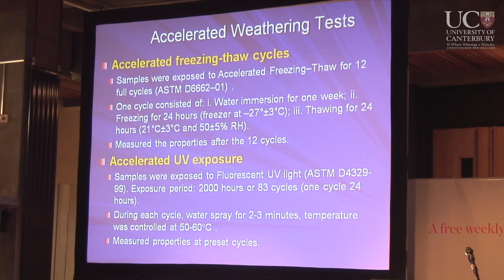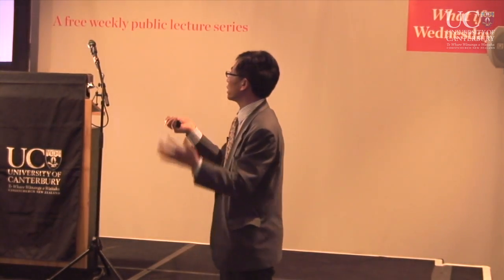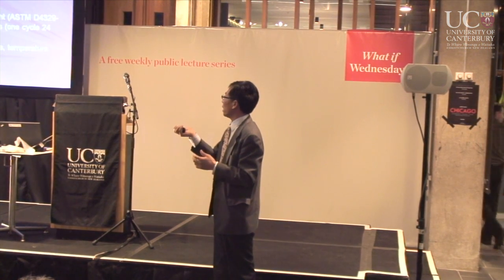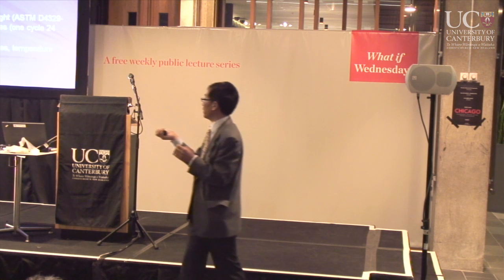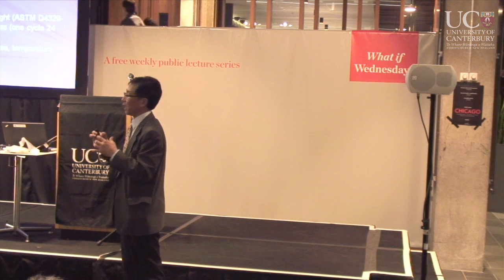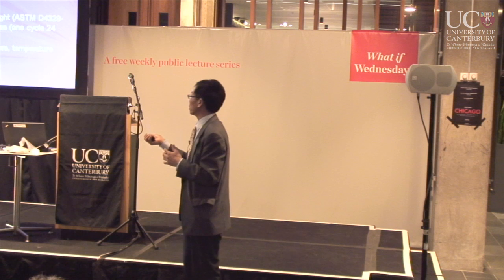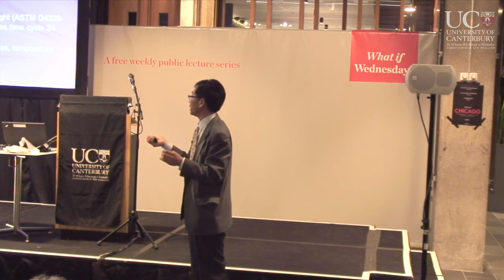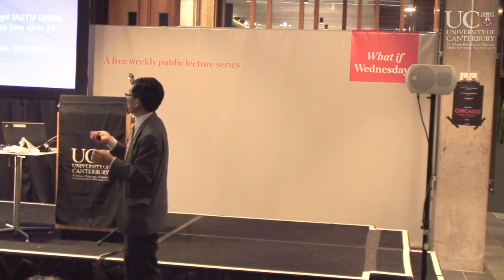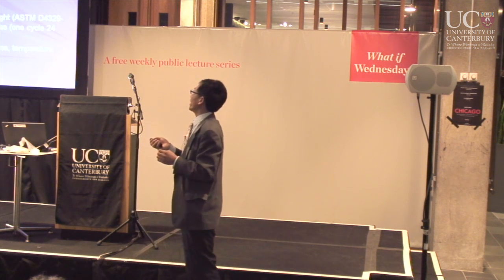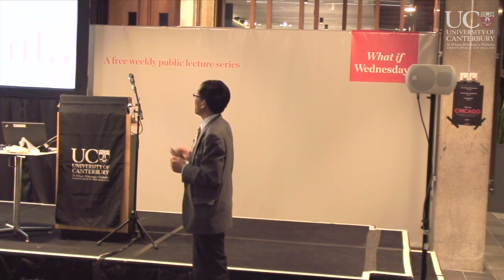And we also did the accelerated UV exposure test. We put the materials in a UV box with a UV light to expose the material, for 2,000 hours of exposure. During these cycles, we spray water and control the temperature at 50 to 60 degrees C. Then we measure the properties at preset cycles and after the 2,000 hours to look at the mechanical property change and the stability, for both accelerated weathering tests. And these are the results.